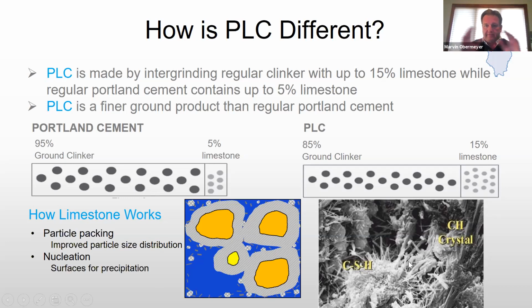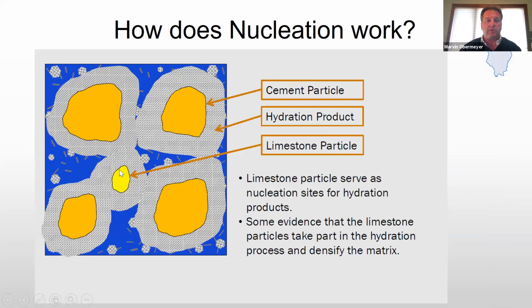This is a microscopic view of that. This is calcium silicate hydrate. These fingers that are reaching out are calcium silicate hydrate fingers. Now, as you can imagine, one of the things we tell our contractors is do not put too much water in your concrete, because you separate our little buddies away from each other and they can't reach out and touch each other. Well, that's what's going on here. If these are too far apart, the calcium silicate hydrate bonds are only going to go so far. But if there is a particle of limestone in there, they'll reach to that and be able to touch base there, just like this situation right here.